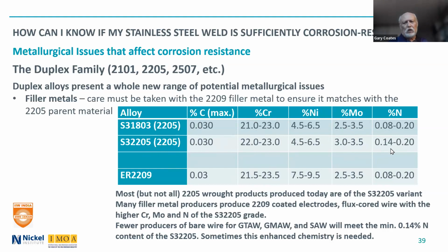specifications. And really, most importantly, it's the nitrogen content is in the high end, because we said nitrogen aids in the transformation of ferrite to austenite as the weld metal cools. Now, one of the issues is that for the filler metals, the chromium content is just slightly higher than the original base material, but it can be lower than the modified version. The molybdenum content is still at the minimum level, and the nitrogen is at again the minimum level.